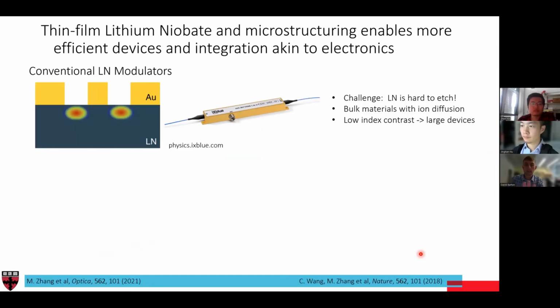And so that's typically done like this, where you dope titanium into particular areas of your lithium niobate, and then you put down contacts that you apply an electric field to. But the challenge here is that the index contrast when you add in titanium is actually not that large. And so you need to have very large waveguides that are comparable to maybe optical fibers. And because of this, the devices are quite large and your electrodes need to be spaced quite far away to get the response that you need. And so that requires you to have devices that are relatively quite large.